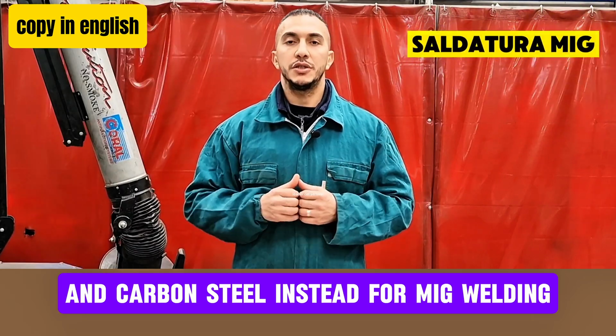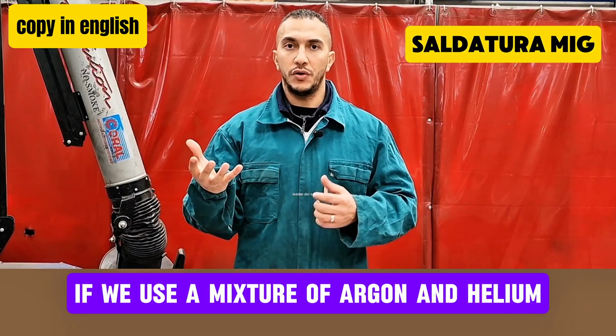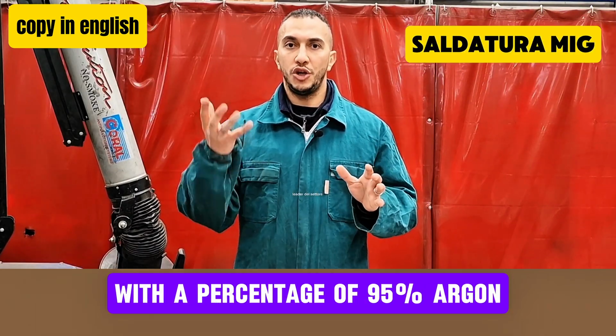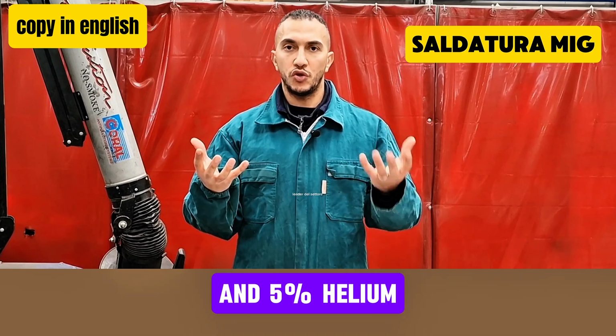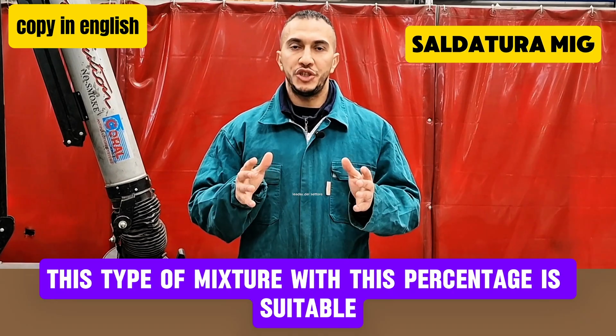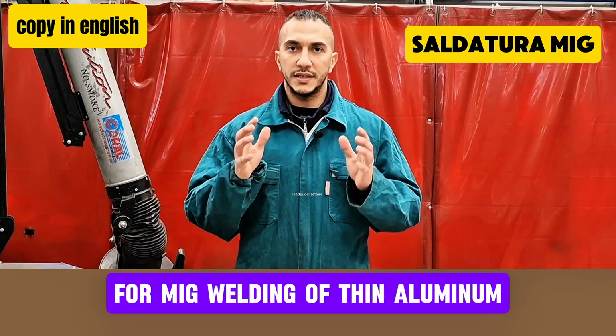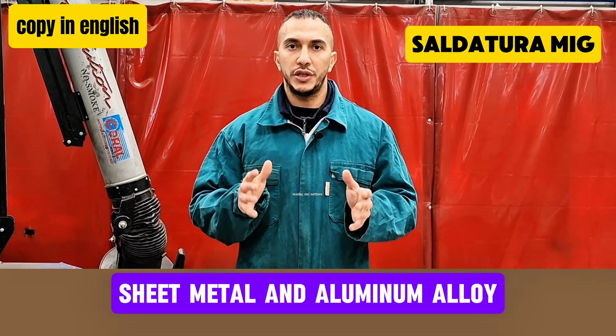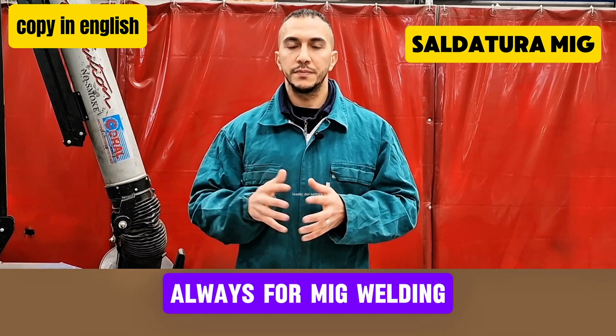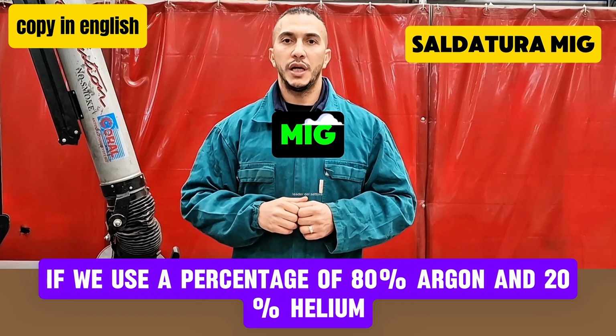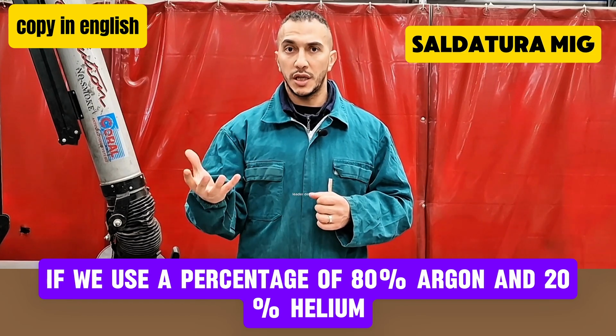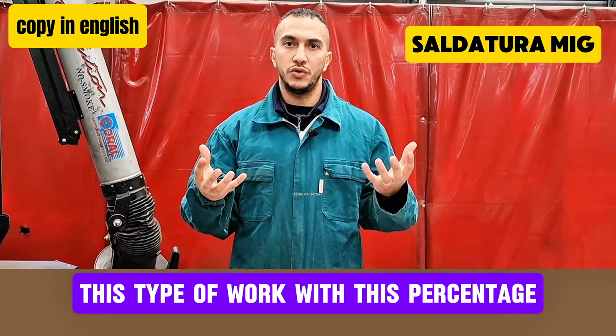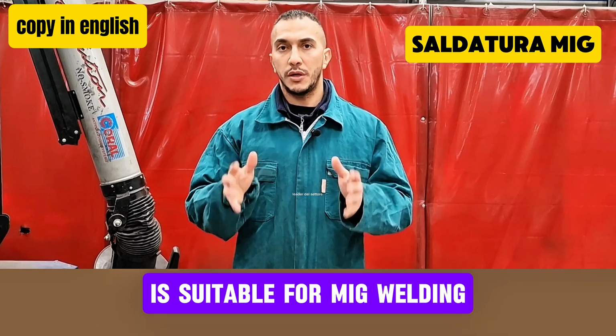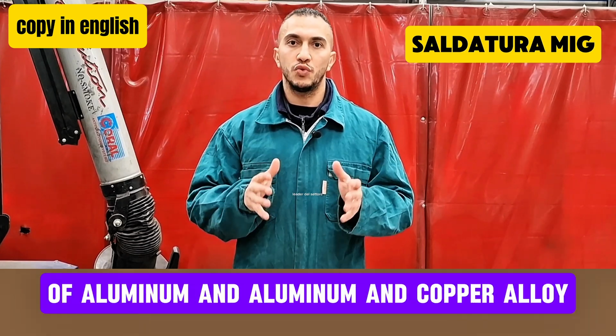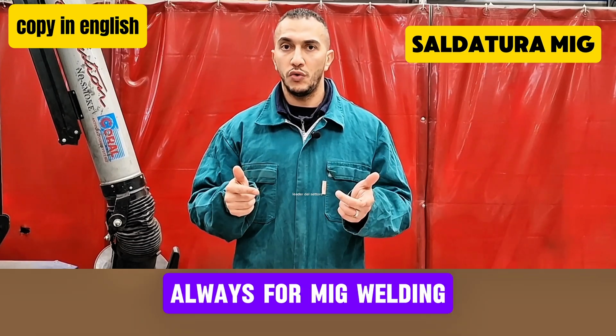Instead, for MIG welding, if we use a mixture of argon and helium with a percentage of 95% argon and 5% helium, this type of mixture is suitable for MIG welding of thin aluminum sheet metal and aluminum alloy. Always for MIG welding, if we use 80% argon and 20% helium, this type of mixture is suitable for MIG welding of aluminum and copper alloy.